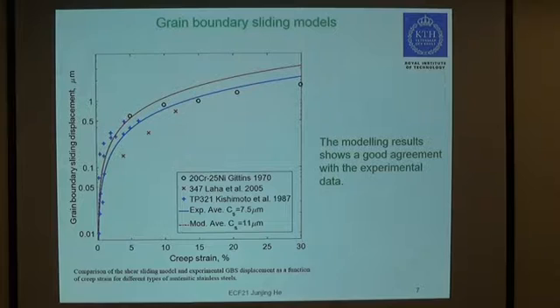Here are the results of the grain boundary sliding models. This figure shows the comparison of the shear sliding model and the experimental grain boundary sliding displacement as a function of creep strain for different types of austenitic stainless steels. The lines here are the average values of the modeling and the experimental results. The modeling results show good agreement with the experimental data.